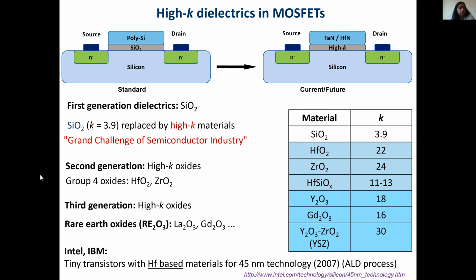And then the research was focused on looking for the second generation of materials that can serve as dielectric oxides, and that deals with the hafnium and zirconium oxides, basically belonging to group 4. In this case, Gordon Moore, one of the co-founders of Intel, had predicted that if at all SiO2 is going to be replaced by another material, it can be considered a grand challenge of the semiconductor industry. And actually that became true. In 2007, Intel and IBM jointly announced that for the technology at that time, in the early to mid 2000s, these materials had replaced SiO2.